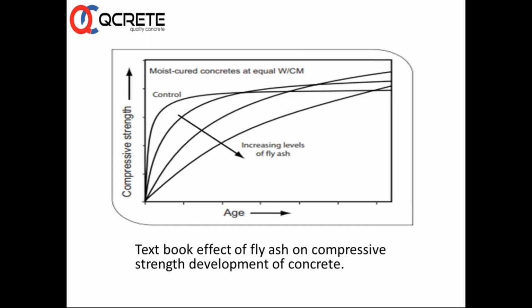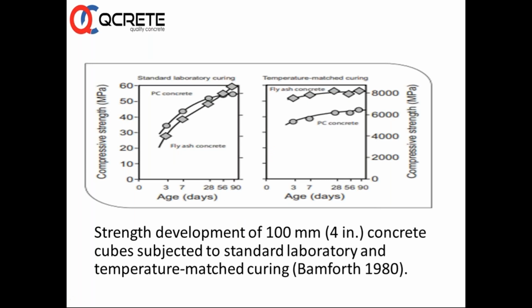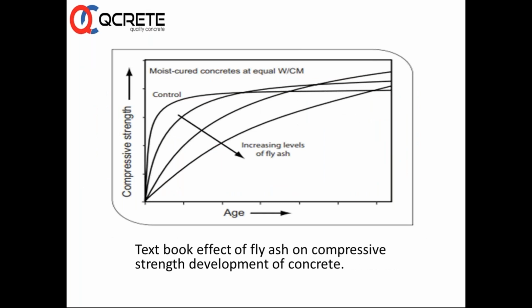This is the significant advantage, and I can say one of the most important aspects when you are using fly ash. It is very, very important to consider this when you are making big monuments, public buildings, structures which are of importance, where you can specify later age strengths. There are other countries other than India where they have started specifying 90-day, 180-day, 56-day strengths. In such cases you can proportion your mix with a lesser amount of OPC and higher amount of fly ash or probably GGBS, where you will have long-term strengths and you can utilize that long-term strength benefit given by SCMs.